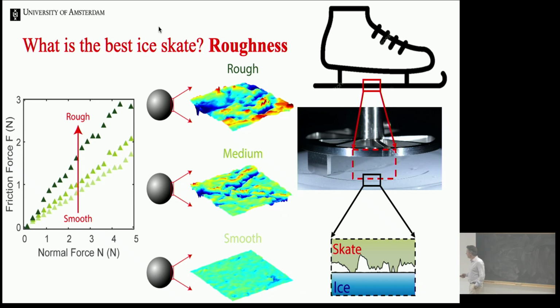And so if I take my piece of skate or my skate model, which is a little sphere, and I measure the friction force as a function of the normal force for different roughnesses, I actually find what everybody knows: the rougher the surface, the higher the friction coefficient. And so what happens if my skate isn't well polished is that I start plowing much earlier, and I really don't want that. And so I should compare the real pressure on the contact to the penetration hardness of the ice to decide about the friction coefficient.